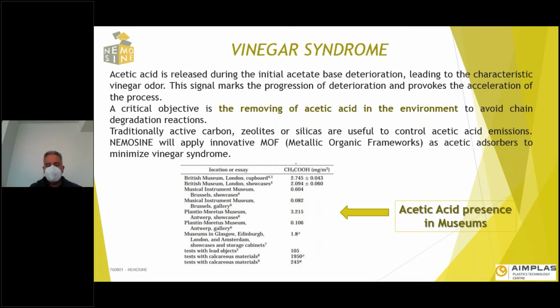As has been explained in other training actions of NEMOSINE projects, we have a lot of different sorbent materials that can be used for this purpose. We can talk about active carbon, zeolite, silicates, materials that have porosity as a common point. Porosity that is used to store or trap, selectively, the molecules of acetic acid. The good thing about MOFs, metal-organic frameworks, as sorbent materials compared with traditional active carbon, zeolites, or silicates is that they are more selective to acetic acid compared with other gases.